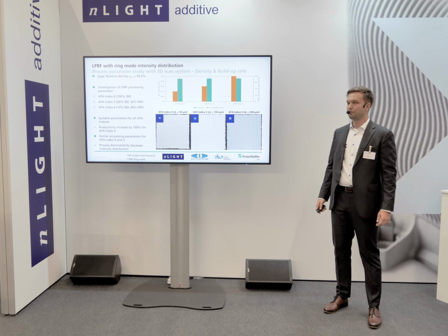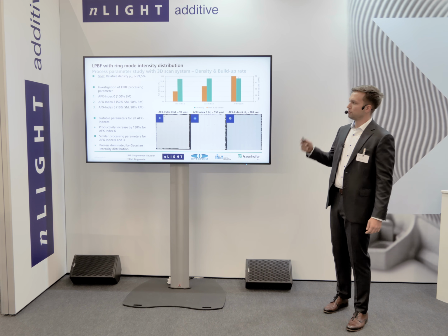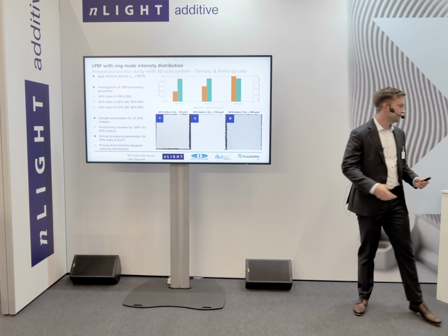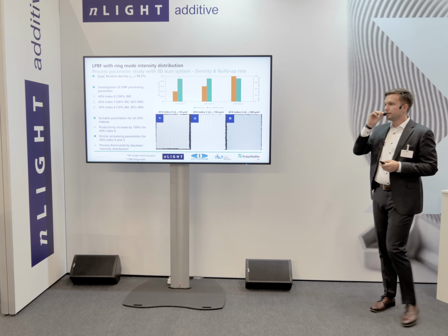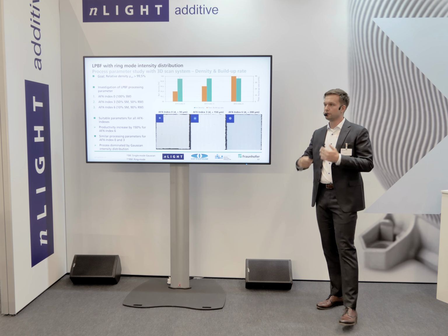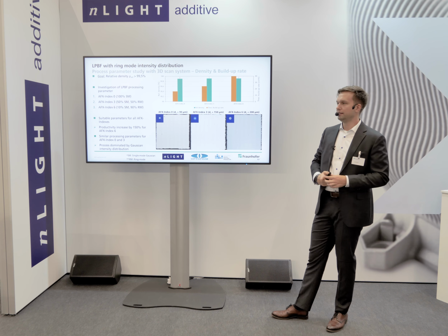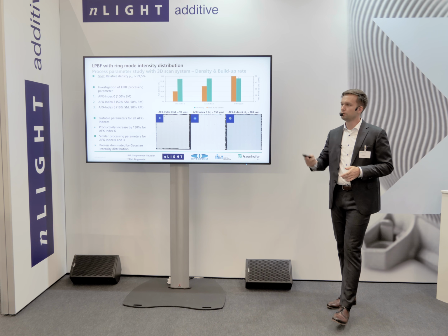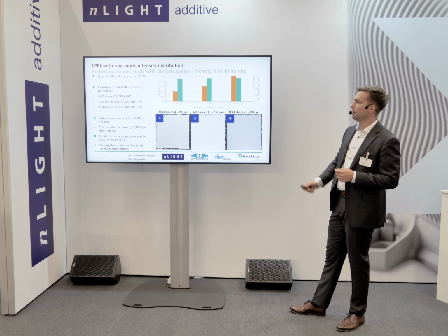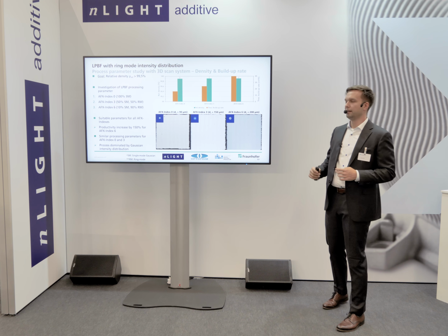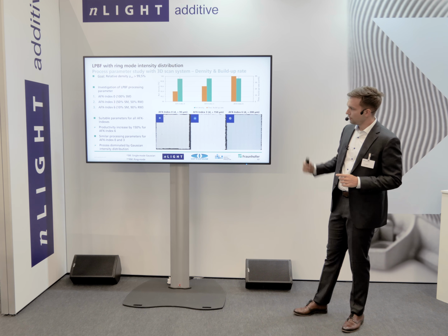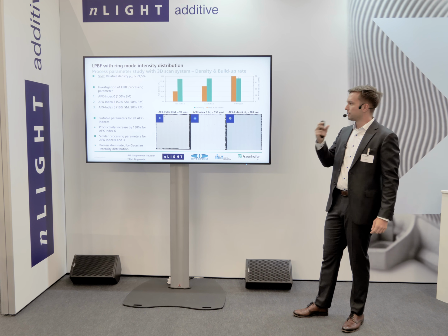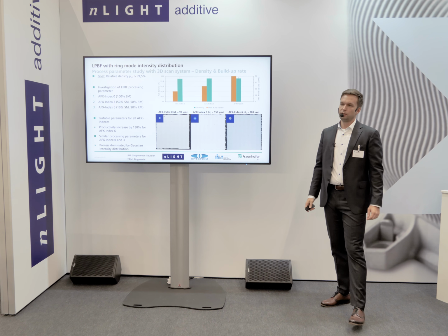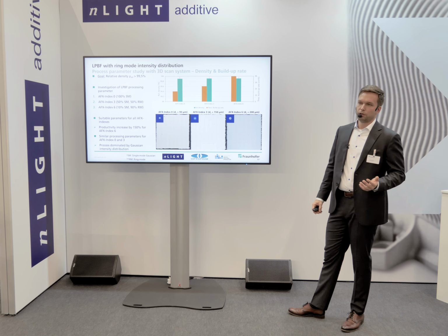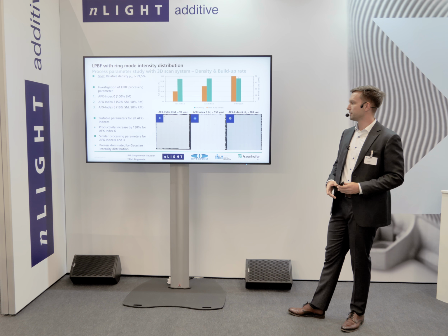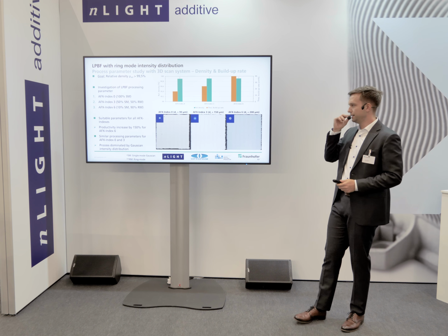We did the process parameter development for Inconel 625. The criterion here was also above 99.5% for the relative density, but instead of comparing scan speed and layer thickness or productivity as a whole, we compared the AFX indexes 0, 3, and 6, which correspond to 100% single mode Gaussian, 50-50 between single mode and ring mode, and almost 100% ring mode. And through the data you see in this upper graph, and also through the cut sections below, you see the density isn't really an issue. Processing up to 99.5, even 99.9% density is possible with all settings.